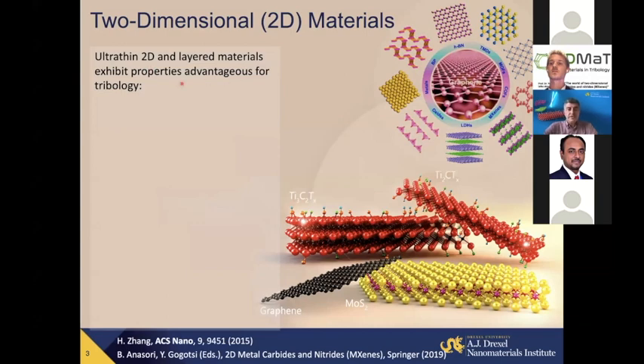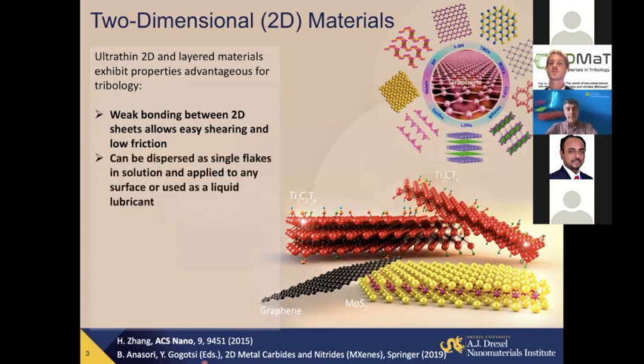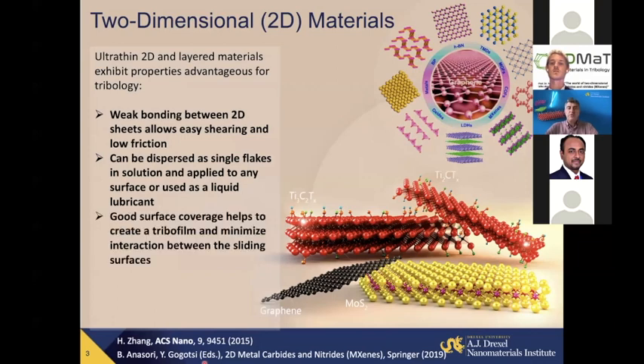So why are 2D materials of interest for tribology? A main reason is that they have weak bonding between 2D layers, which allows shearing and sliding of the layers relative to each other. Also, layered 2D materials can be dispersed in solutions, water, or organic solvents, and applied to surfaces as a liquid lubricant or form a continuous coating protecting the surface with good surface coverage, helping to create a tribofilm and minimize interaction between the layers. And finally, it's also possible to intercalate a variety of molecules between the layers, which again can control those interactions between the two-dimensional sheets, eventually decreasing the friction.